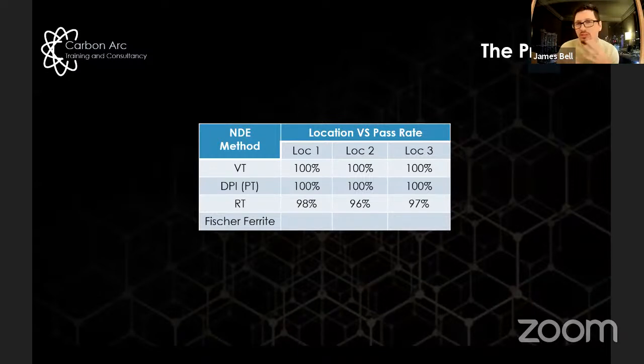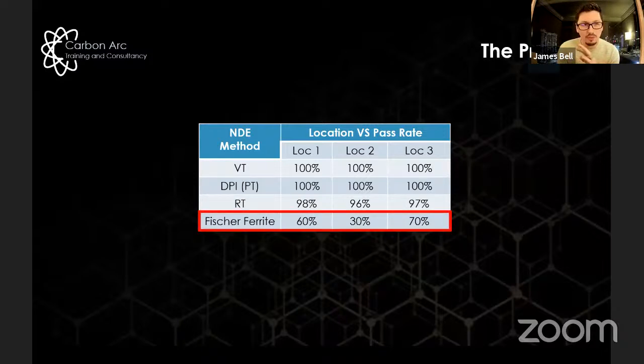So we were expected to run a slight failure rate, which we saw and was in line with our expectations. But when we started producing Fischer Feritscope tests, we were seeing a pass rate averaging around 50% over all 3 locations, which was a very big struggle for us, and was causing some massive issues. And it was not only costing us a lot of money in rework, but also lost time.